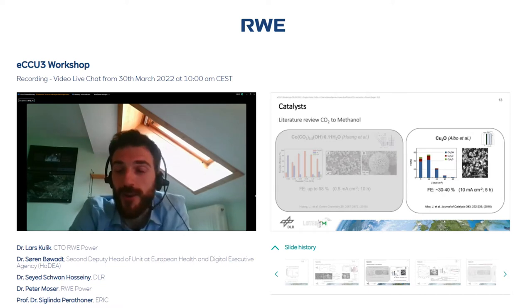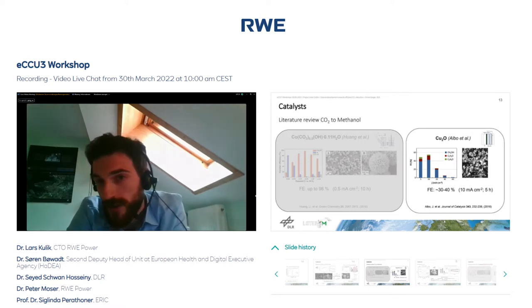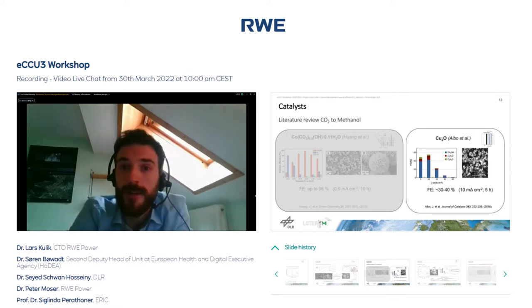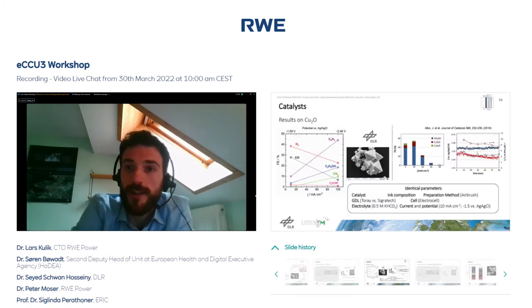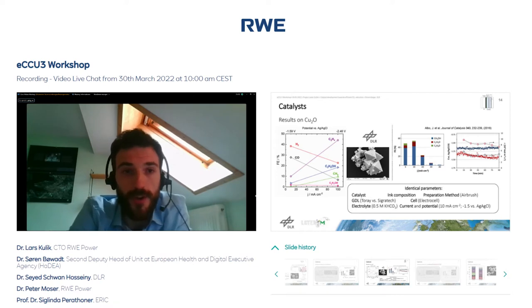So slide 13 just shows this overview again, and showing that we were now focusing on the copper material on the right side, which was presented several times to be able to produce methanol. On slide 14, there is now the comparison of our results on the left side in comparison to the paper on the right side. And again, we really cared about all the detail and the identical parameters, and also got into contact with this group actually to solve the problem that we had no methanol in this case.